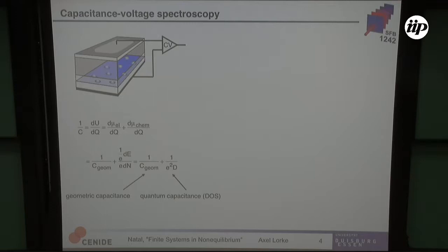I usually like to think of it knowing that the change in charge as you change the voltage is the capacitance, but the voltage is the change in electrochemical potential. So you have one term that is the electrical potential, that's the geometric capacitance, and you have one term that's the chemical potential, and that's related to the density of states. So usually you don't encounter the density of states when you do capacitance. That's because usually you have metallic systems where the density of states is very, very high, so you can leave it out. But here we have a very, very dilute system of states in this quantum dot layer,